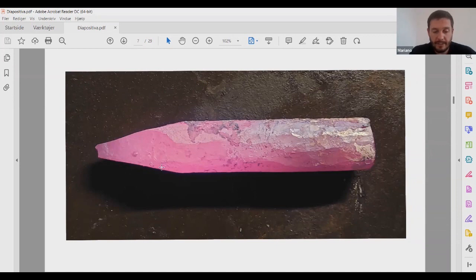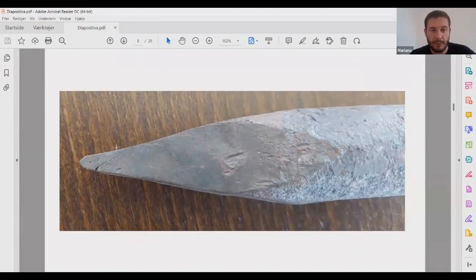If it forms, it will be better to cut this part off so as not to introduce possible fissures. It is extremely important to respect the forging temperature and not forge aggressively, as this could generate cracks and stretch in the material, generating a defective part. We can see here how the cracks start to appear.